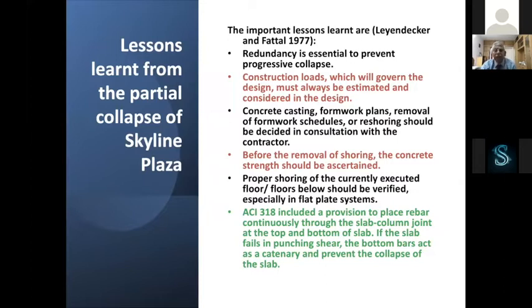Due to this failure, ACI 318 included a provision to place rebar continuously through the slab-column joint at the top and bottom of slabs. If the slab fails in punching shear, the bottom bars can act as catenary and prevent the collapse of the slab.